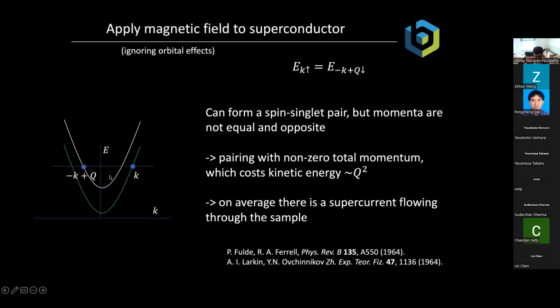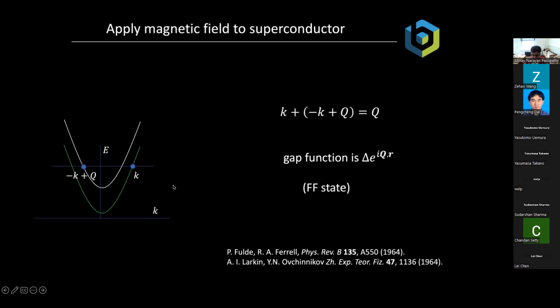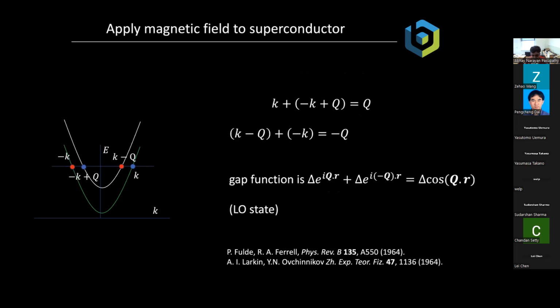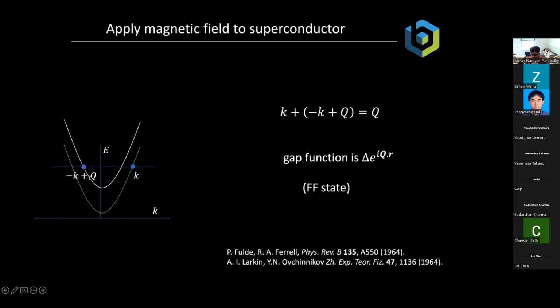And it takes a little bit of gain by forming the superconducting state with this non-zero center of mass momentum, right? And this particular state is called the FF state. And at the same time, Larkin and Ovchinnikov proposed a very closely related but slightly different state, which is called the LO state. And in the LO state, what they proposed is that you have pairs of electrons between k and minus k plus q, so that has net center of mass momentum q, and you also have pairs with minus k and k minus q, so the net center of mass momentum is minus q. So this is basically pairing between this point, and also this point and this point at the same time. And as you can see, these are very closely related states.